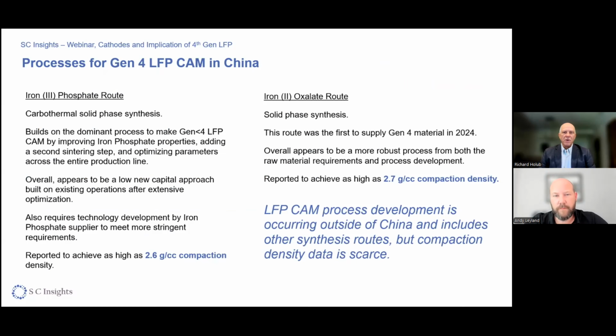All right, so you've got these two routes for solid phase synthesis in China, the iron phosphate route and the iron oxalate route. The iron phosphate route is a carbothermal process, meaning it's like a mini version of a blast furnace. You're using some carbon source in order to reduce the iron from iron 3 to iron 2. It builds on, of course, the huge base, 80% of the Gen less than 4, I'll use that term, LFP is made by this process in China, but it does add a second sintering step, and it has a lot of optimization of parameters across the entire production line. And I don't mention here, but also a lot of discussion about separating the particles and recombining them in order to get the right particle size distribution.